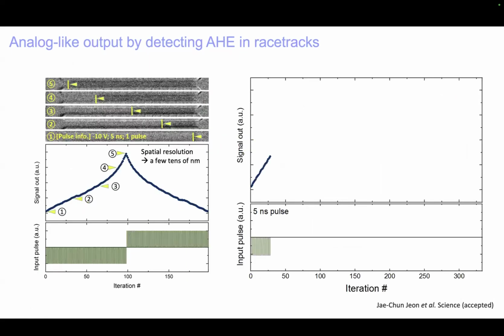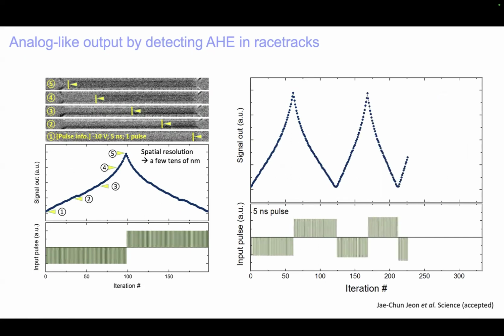And this has enabled us then to follow the individual domain wall as it moves backwards and forwards along a racetrack as we apply current pulses. These are 5 nanoseconds long in one direction and then the opposite direction. So the individual domain wall can be moved all the way along one racetrack from the left to the right, back and forth. And as we increase the intensity of the current pulse, you can see we need smaller numbers of current pulses to move the domain wall from the left to the right. The resolution with which we can detect one domain wall is just a few tens of nanometers.